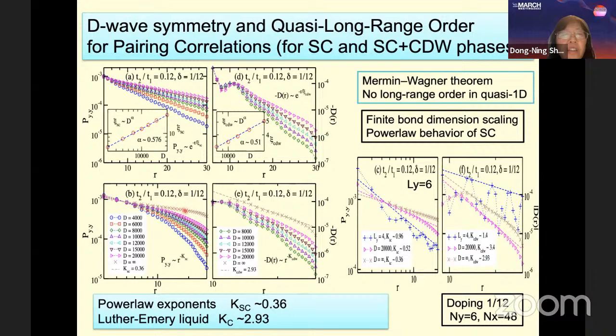So a better scanning method is to directly scale the pairing correlation at different distances to infinite bond dimension. Then the resulting pairing correlation curves follow power law decay. The power law decay exponent K superconducting is around 0.3, so it decays much slower than 1 over X behavior, where X is 1 over R. That indicates very strong superconducting correlation.